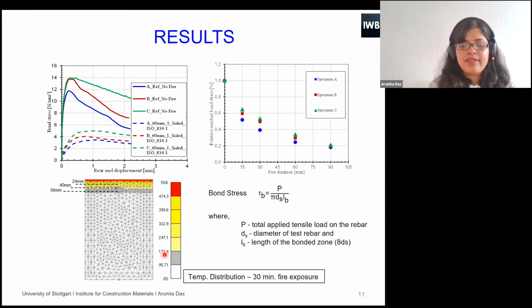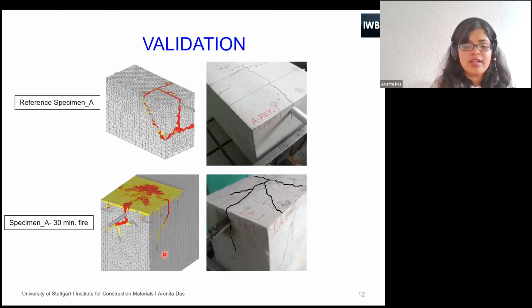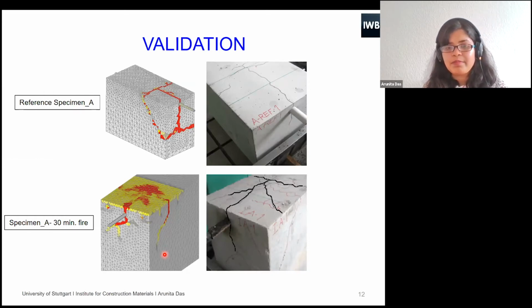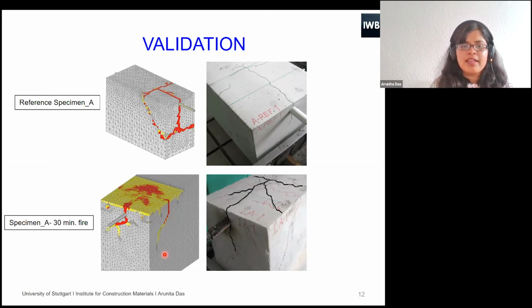So basically fire has a twofold effect. One is material degradation and one is temperature gradient. Material degradation cannot really show this effect, but due to this temperature gradient, we can see that there is a huge degradation of the bond stress.